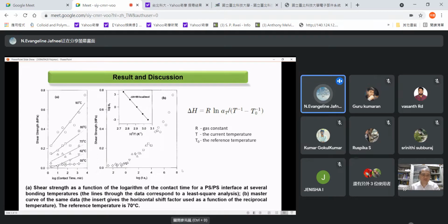The second graph represents the master curve at 70 degrees Celsius, which is the reference temperature chosen. With the help of the second graph, the Arrhenius plot is also given, and the enthalpy of the blend was calculated as 99 kilocalorie per mole with the help of the Arrhenius equation.